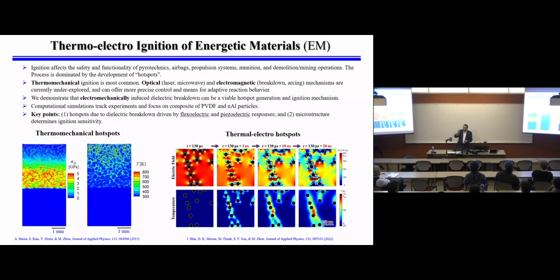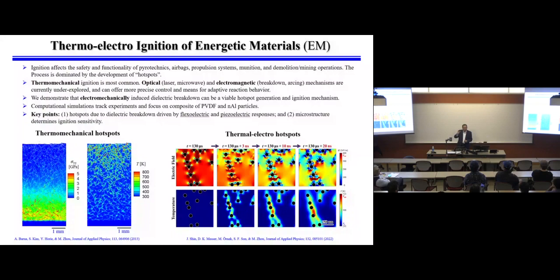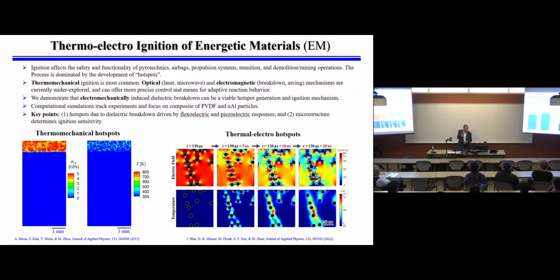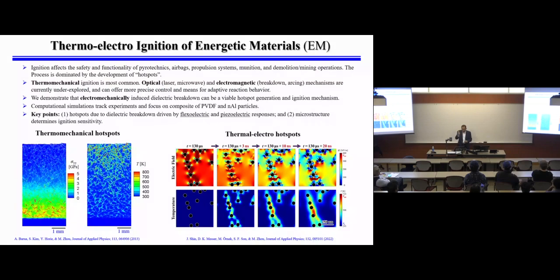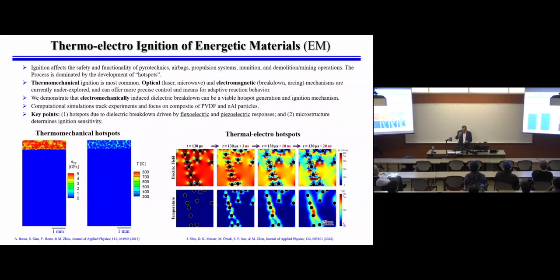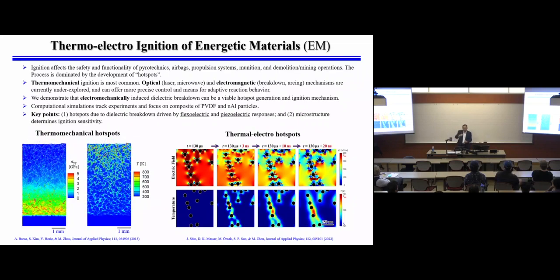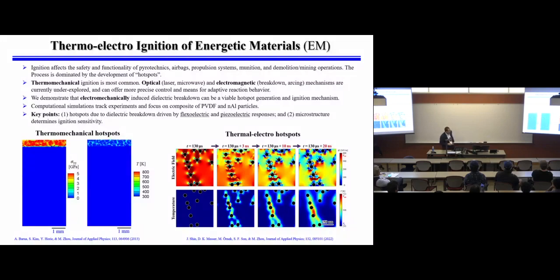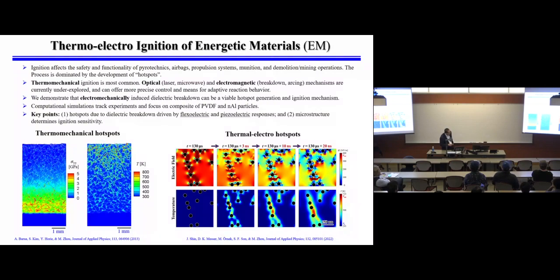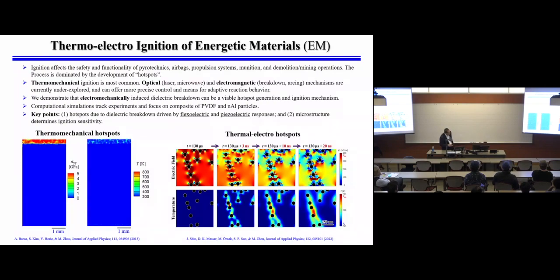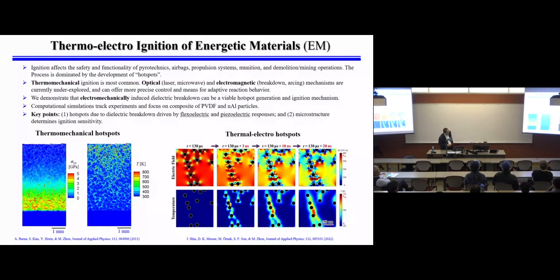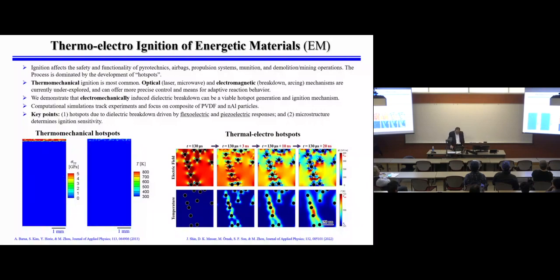when the electric field is strong enough, you may have dielectric breakdown. You may have sparking in the material. That causes the material to become conductive. The current flows in the material in very local areas, and the current converts the electrical energy into thermal energy, generating temperature. So that's what we're going to do here, to see that once you have enough electric field in the material, you have dielectric breakdown, and you generate hot spots, very high temperatures, that will initiate the chemistry.